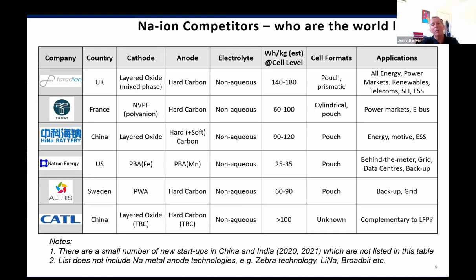The anode again is hard carbon, with a non-aqueous electrolyte, and you can see the specific energies that we're talking about right now, right? 140 to 180 watt-hours per kilogram. So Tiamat in France, I mentioned those two. They're using the sodium vanadium fluorophosphate material. And because of that, you're looking at much more moderate specific energy at 60 to 100 watt-hours per kilogram, but it's good for the power market. And they're targeting those power markets and hybrid buses and things like that.